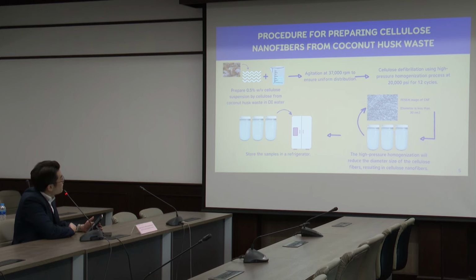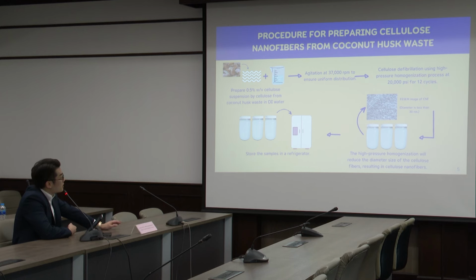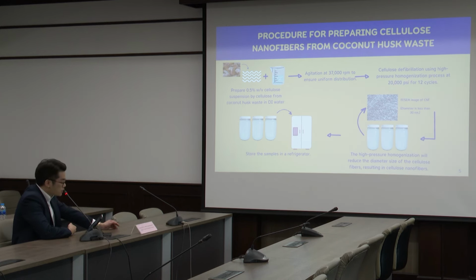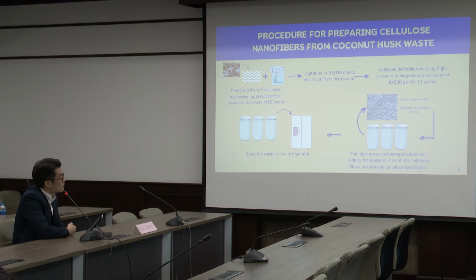The experimental procedure for preparing cellulose nanofiber from coconut husk waste. Briefly, we got the coconut husk waste from a coconut farm in Prachuap Khiri Khan province, Thailand, and the coconut husk waste was then cleaned and passed through alkali treatment and bleaching process to become cellulose fiber. And then we dispersed the cellulose fiber in DI water to achieve a concentration of about 0.5% weight by volume, and then transferred the cellulose through the high pressure homogenization process at 20,000 psi for 12 cycles. The high pressure homogenization reduces the diameter of the cellulose fiber to become cellulose nanofiber, as you can see in the FESEM in this picture.